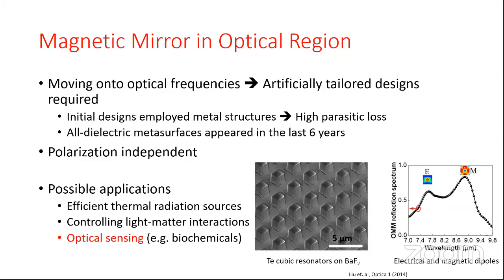And on the right image, you could see the optical response of a magnetic mirror. You could see two reflection peaks. The one around 7.8 micrometer is due to the electric dipole, and the one around 9 micrometer is due to the magnetic dipole. And on the left, you could see the SEM image of the structure. It's tellurium cubic resonators sitting on top of a barium fluoride substrate. And people in the literature say there are possible applications such as efficient thermal radiation sources or to control light matter interactions, as well as optical sensing, for example, biochemicals or polymers of interest.